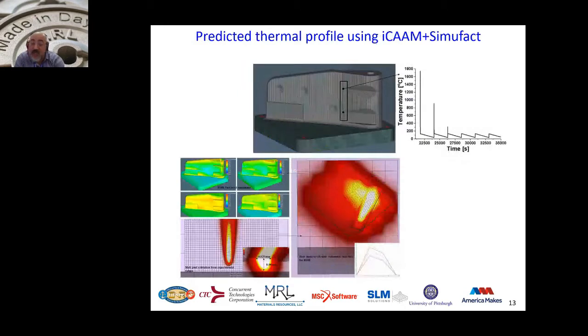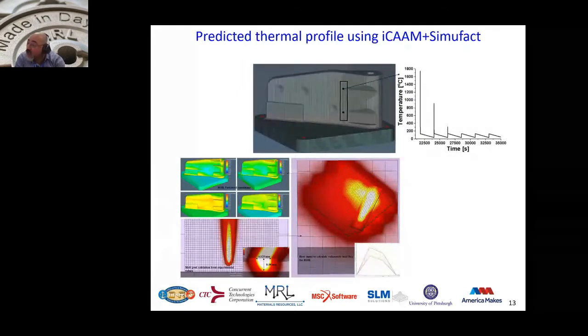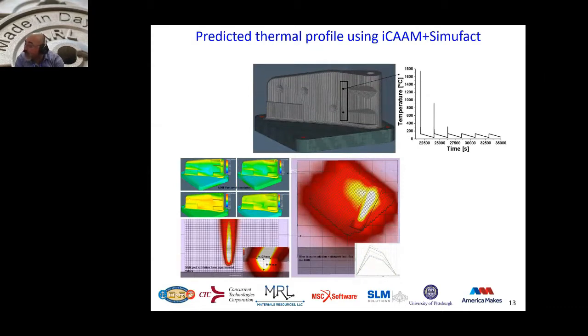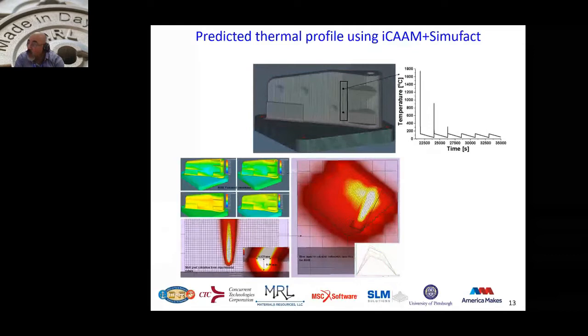And following slide number 13, you see our use of SimuFact tools to be able to predict the location-specific thermal profile as a function of the scanning strategy and the machine setup, including even the laser diameters, and the calibration that we did in-house with the hierarchical simulations at the melt pool level, all the way to taking into account the material behavior at higher temperature, not just at lower temperature, and then the location-specific prediction of the thermal profile as a function of multiple layers that were added.